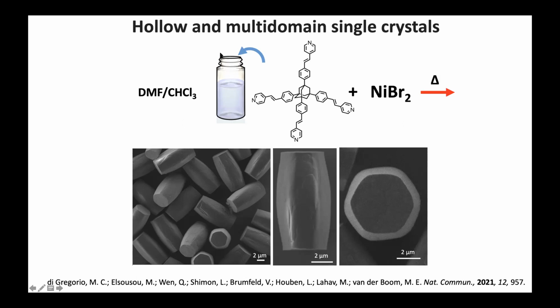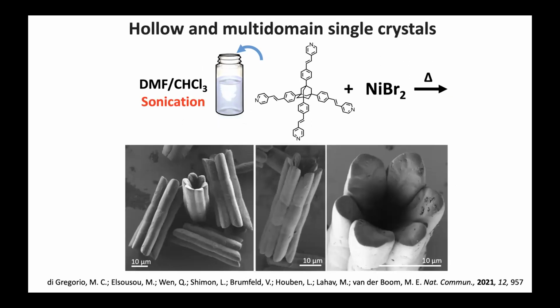What you do is you generate radicals, traces of radicals in the solutions. The solvent starts to decompose, basically. We see that by EPR measurements. When we add the ligand and the metal salt to the solutions after sonication, we see the following happening. You see completely different crystals. You see these hollow crystals having these 6 rods connected, like 3 growth zones, 3 growth areas, just by sonication of the solvents for about an hour prior to carrying out the reaction.